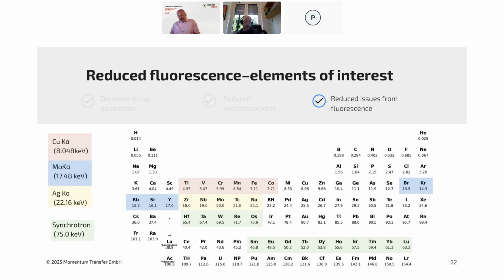Alternatively, you can go to higher energy, which is like molybdenum or silver K alpha radiation. In those cases, you have other elements that are slightly below the working energy that cause the most fluorescence, that are maybe kind of less bad. With 75 keV, then we significantly move up the elements that fluoresce significantly into the higher side of the lanthanide series, and then hafnium up to osmium. So at 75 keV, you're right between the energies where you have just enough energy to knock electrons out of osmium, but not enough for iridium. So iridium doesn't cause any significant fluorescence.